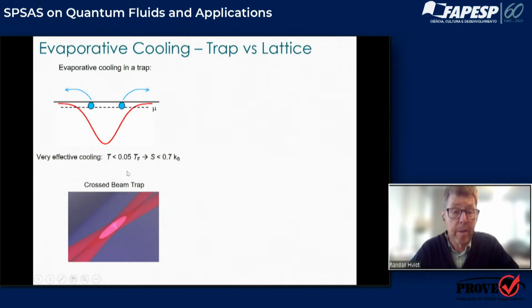And you get very effective cooling where you can easily get below about 5% of the Fermi temperature. And that, in fact, is below the log 2 entropy scale that we had just looked at. So this looks very promising.